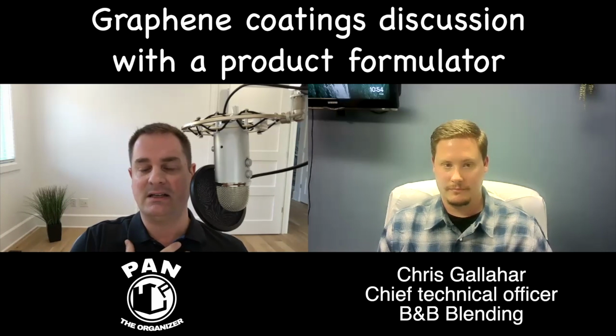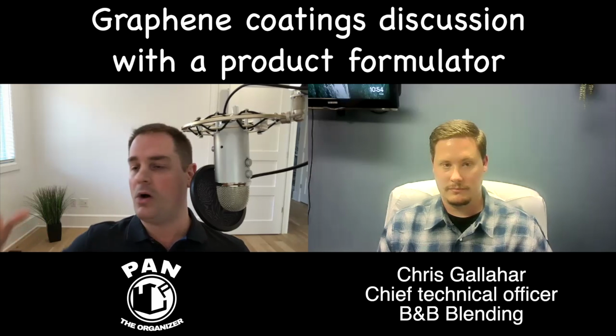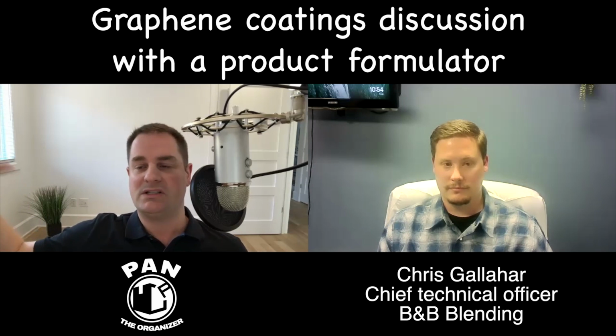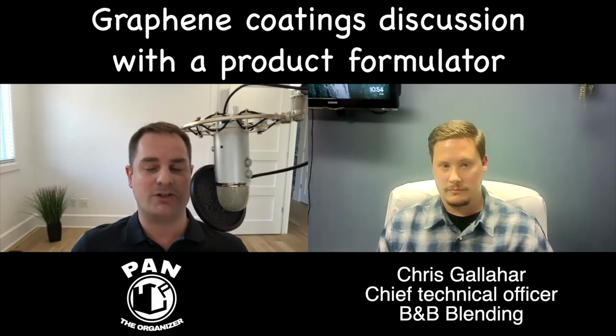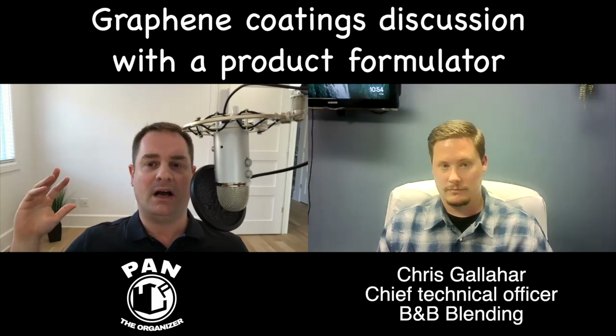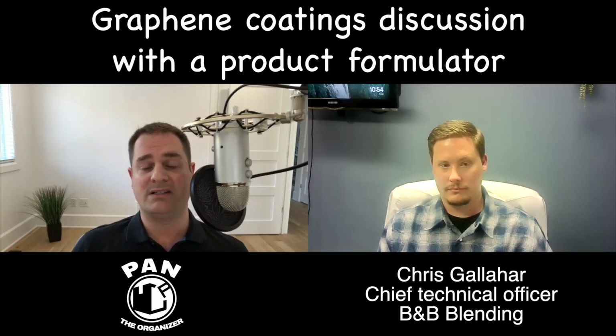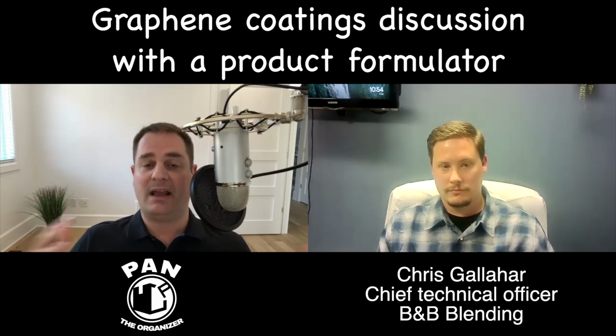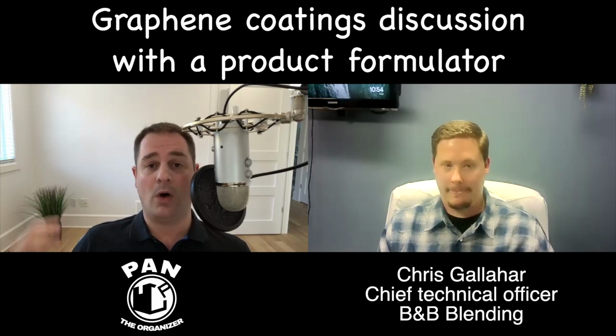And from my testing, I don't have any issues with my personal cars, because I do have a water softener system at home. My water was already super soft to start off with, so it's not an area with hard water issues. And my cars are garage kept, so I don't have issues with water spotting. However, the daily drivers that I apply products to, I'm lucky because I get to see them often come back for more services. And when I applied the graphene coatings that I've been testing, by splitting the hood in half with a ceramic and a graphene-based coating, what I did notice is that there was a reduction in water spotting.